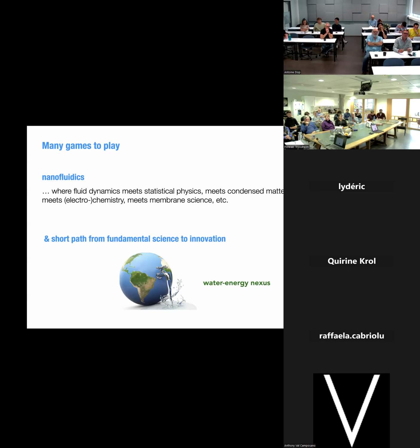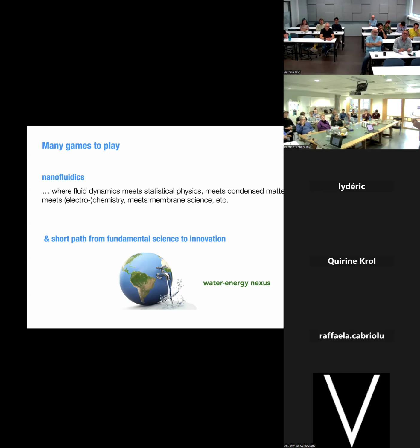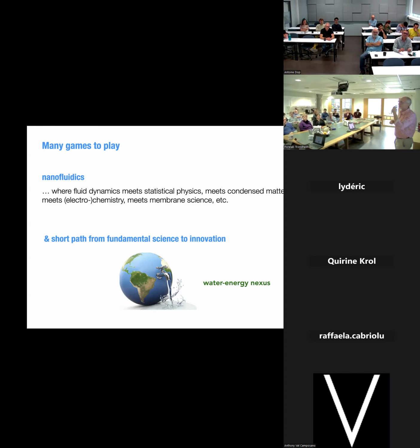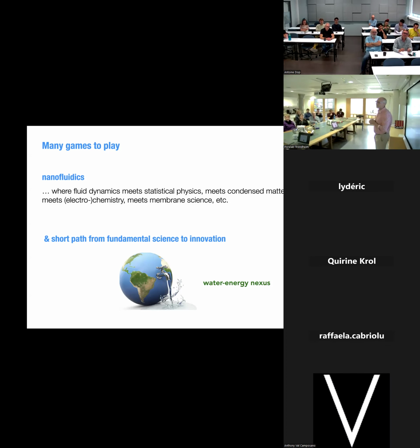To make a quick summary of what happens, the fact that the friction on water is small is actually not so surprising because carbon is extremely dense, in particular graphene. So water sees something very, very smooth, so the corrugation should be small. Now, in some sense, the big question is reversed: why is it so high on graphite? And in our experiments, we had multi-layer carbon nanotubes. And the point is that we showed that